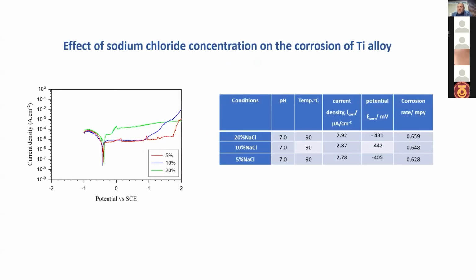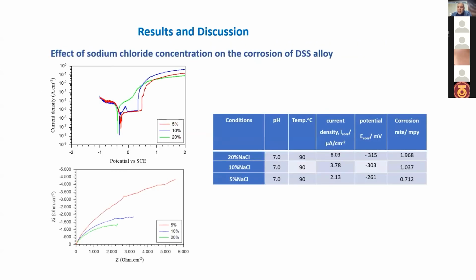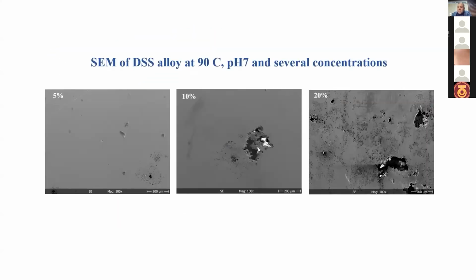Now, we can explain this result. We note that the increase in the chloride concentration or the chloride ions has a significant effect on the corrosion behavior of duplex stainless steel. And this is due to the chloride ions slowly penetrating into the surface, at which the protective film is destroyed and the steel begins to corrode. And the chloride corrosion tends to unevenly pit the entire surface area of the specimen with shallow, irregular shaped pits. Chloride penetration into the metal is due to the presence of different mechanisms, mainly diffusion and capillary absorption.